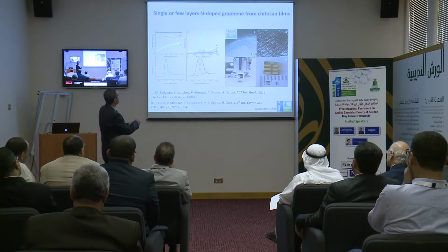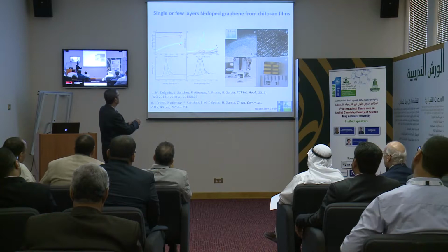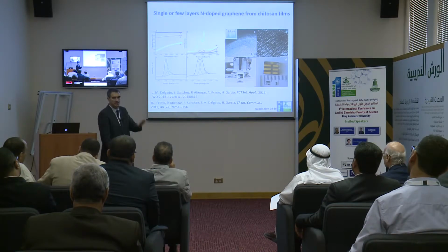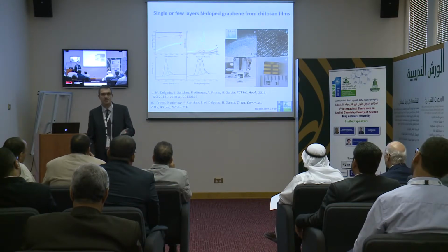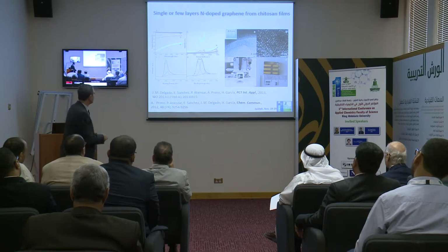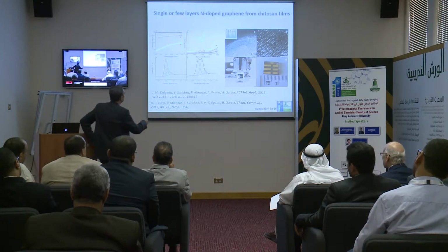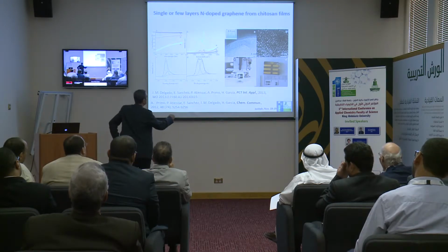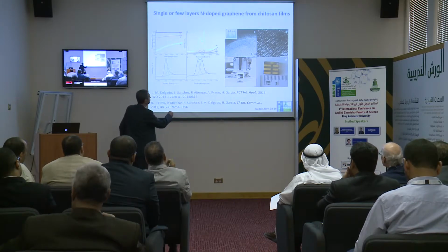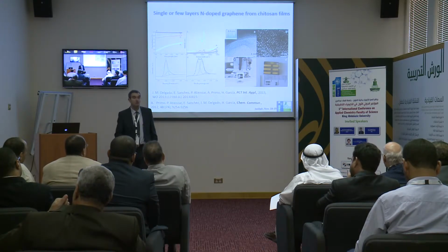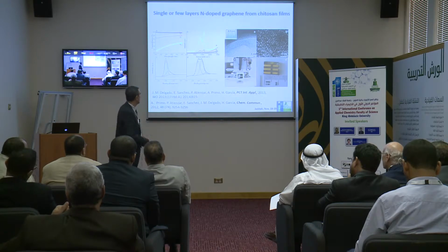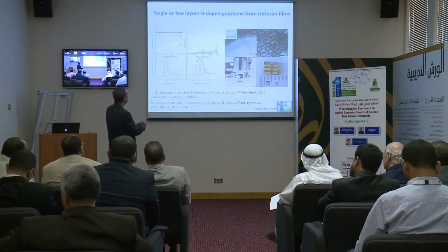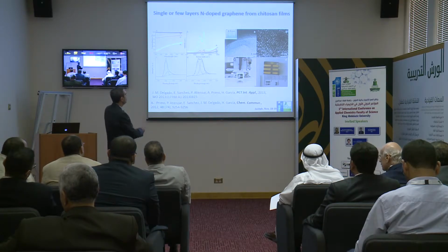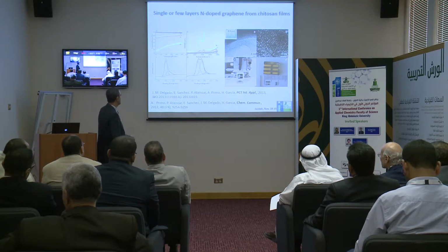And if the number of layers increases, for instance 4-layer graphene, then already the naked eye can see that there is something, that there is gray. And there is also Raman spectroscopy. This is the Raman of a single-layer graphene. Of course, the Raman signal is very weak. It's very weak because we have a single layer of atoms, but if we have 2 layers or 4 layers, then the signal of the Raman increases in intensity.